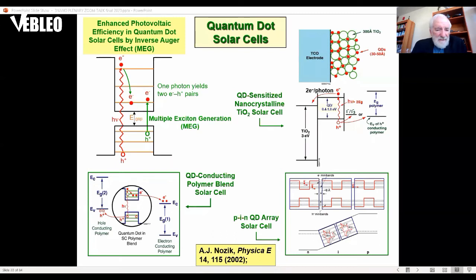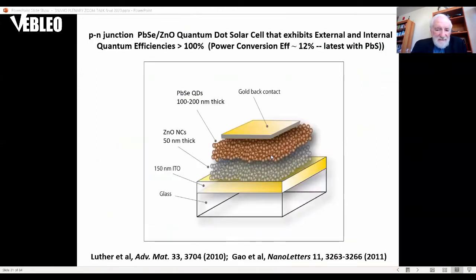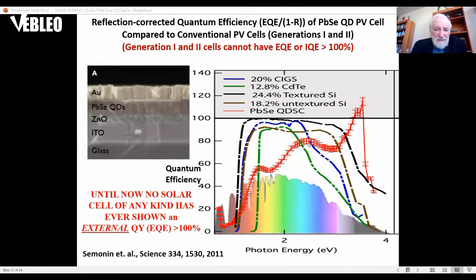Or you can have them in a solar cell and just get the separation of electron and hole pairs in a device consisting of an array of quantum dots between two metal electrodes. And that would be this case. That case was shown to actually produce a quantum yield in the photocurrent greater than 100%. So that's the first solar cell ever measured that produced a photocurrent that had a quantum yield greater than 100%, because of the extra electron produced by impact ionization, or MEG in the case of the nanocrystals. And that was published in 2011 in this paper in Science.